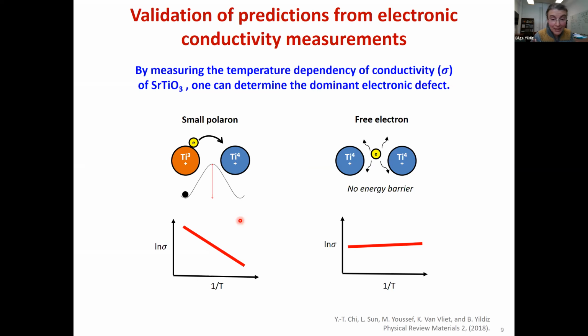And how can we validate this? So I've already told you that there are experiments in literature that we could potentially use. In particular, by looking at the temperature dependence of the electronic conductivity that is measured, we can determine the dominant electronic defect. Because if we are dealing with a small polaron that conducts via hopping, which is a thermally activated process, the conductivity as a function of inverse temperature should show a decrease with decreasing temperature.